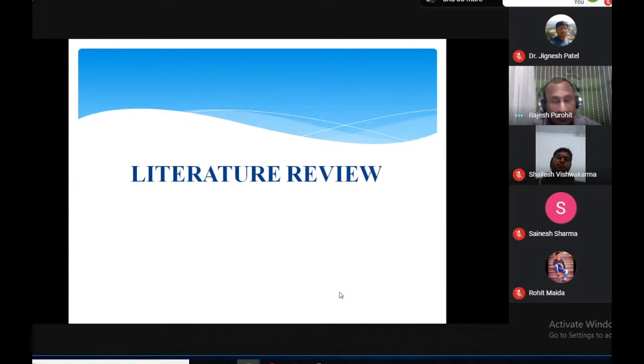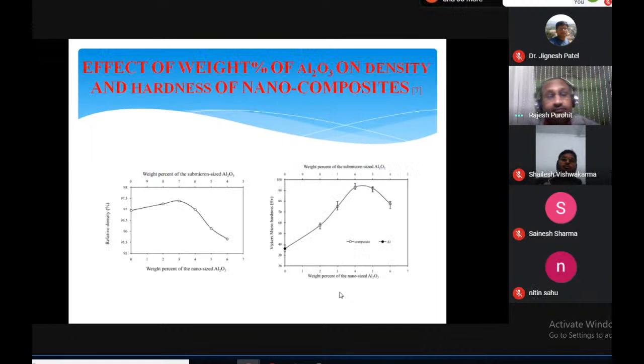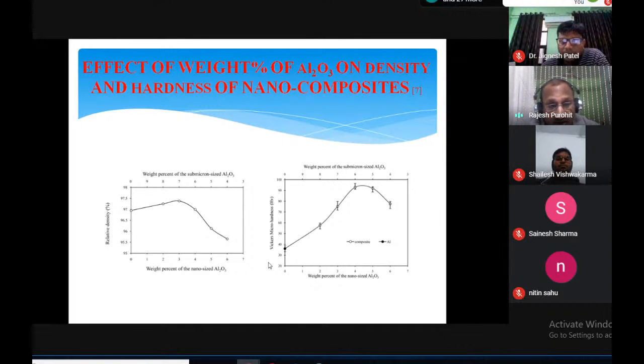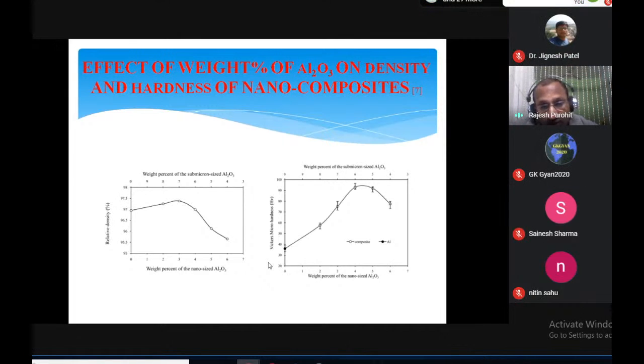Then I will discuss a little bit of the literature survey that we have done. Some of the papers I will discuss. Effect of weight percent of aluminum oxide on density and hardness of the nanocomposite. These are graphs from various literature. In the first, left side graph, relative density is shown with the weight percent of nano-sized aluminum oxide. We see that density first increases and then decreases. At about 3 weight percent nano alumina we get the highest relative density, and after that it decreases. Basically, this is due to more porosity forming when we mix more than 3 weight percent.